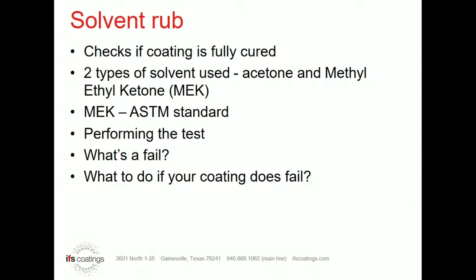What's a fail? This is somewhat an opinion based on years of experience knowing what products will pass and what some of the failures are. Normally, what we would call a failure is when you take a Q-tip, submerge it into acetone or MEK, get it good and wet, then press it against the surface and move it forward and back about an inch or two — that is considered a double rub. Most products are going to be 25 double rubs; for epoxies it could be 50 or even 100 double rubs, as epoxies are great for solvent resistance. You press firmly for 25 double rubs, then look at the Q-tip and the coating.